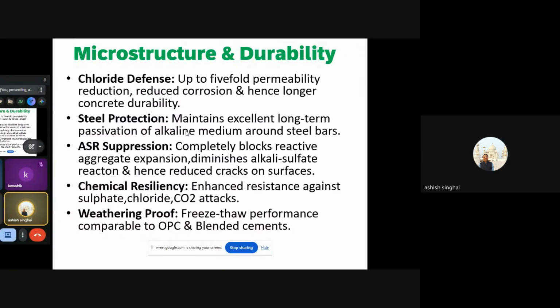Durability: it has a very strong resistance to chloride ingress, which is why it can protect the steel. It generates a very good passivation layer around your steel reinforcement. Hence, the corrosion progression is reduced significantly, and we have a longer concrete durability. Steel protection, as we say.